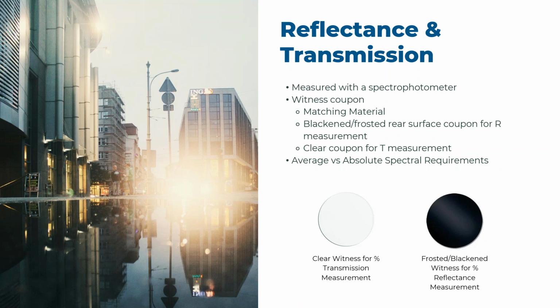If you're taking a standard visible anti-reflective coating from 450 to 650 nanometers, and you're measuring the reflectance of it, if at 451 nanometers we're at 0.51% reflectance, then by letter of the law, we have to reject this coating lot. And that is really the difference of just a simple word, just simple wording, and maybe not even the intent of the specification. So as I get down further into the slide deck here, we'll talk a little bit more about the subjectivity of specifications and when we would take exception and when we may steer the coating specification to probably what is more intended by the designer as opposed to following the letter of the law of the specification if it maybe drives away from being effective, producing a good yield, and being a realistic, achievable, manufacturable specification.